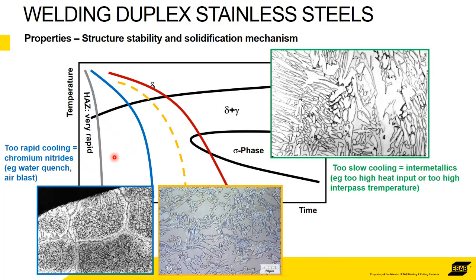So, particularly with something like Duplex stainless steels, Duplex, as you know, is a mixture of austenite and ferrite. That's a good Duplex structure. You've got a nice mix, and that's what you're trying to achieve when you're welding and it cools down. You're trying to get in the middle of the road, just the right amount of heat to enable the structure to reform as it's supposed to. If you ignore the interpass and think, I'll quench it with water very quickly, then what happens is a massive grain structure is promoted, and it's very brittle. So this thing does not have the same properties as this. It's not a properly formed Duplex structure anymore.